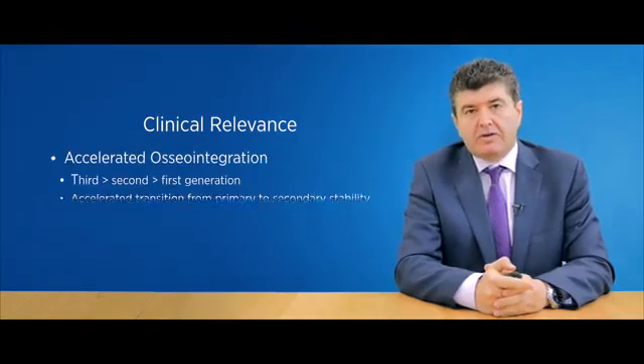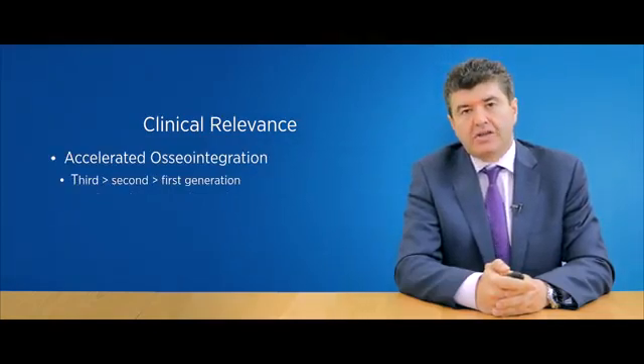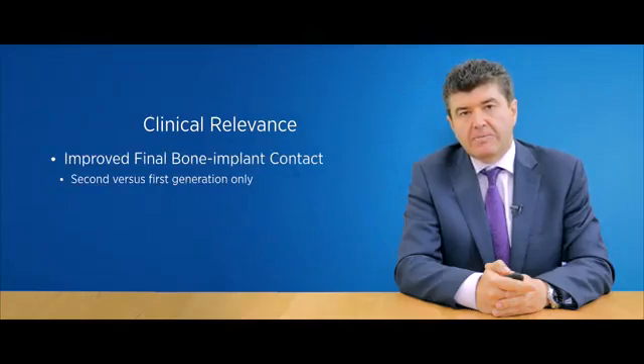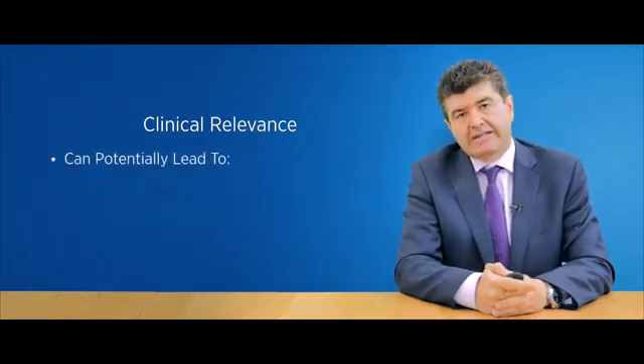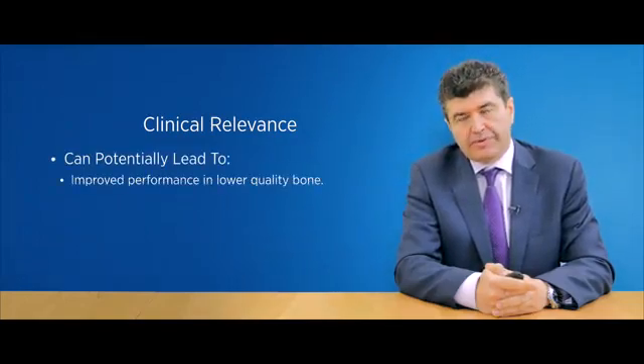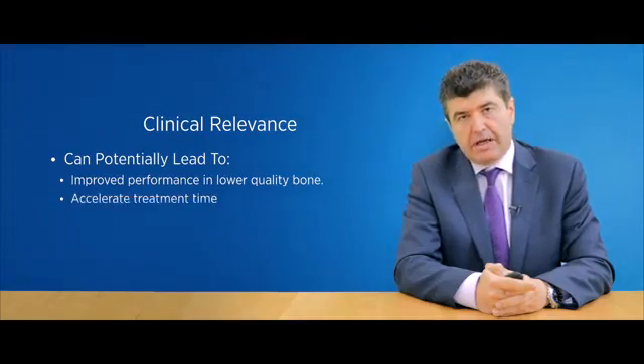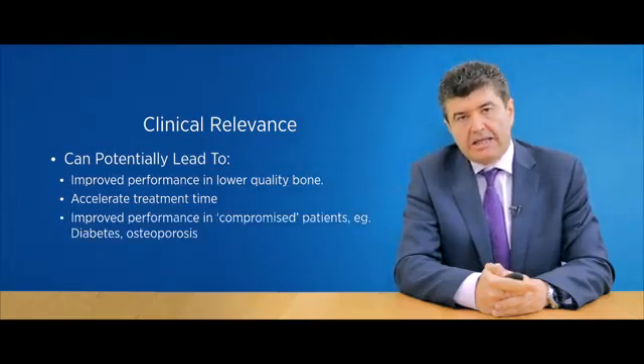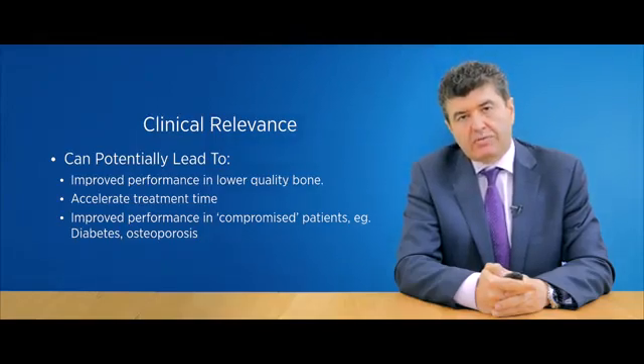So now let us consider the clinical relevance of these implant surface modifications. What we clearly see is a continual acceleration of the osseointegration when you compare third generation versus second and first generation implants. Furthermore, and very clinically relevant, is the finding that second versus first generation implants have greater osseointegration when full maturity is reached. Now this has several important implications. It can potentially lead to improved performance in lower quality bone, such as that found in the posterior maxilla. It can accelerate treatment time. And finally, it may be that third generation implants can perform better in compromised patients, such as those with diabetes and osteoporosis.